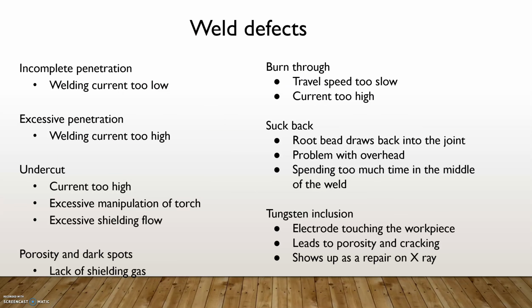Pages 6 and 7 show some weld defects. Incomplete penetration: welding current is too low. Excessive penetration: you have too much current. Undercut can be from current too high, moving your torch around too much, or your shielding gas flow too high. Porosity is from lack of shielding, and if you see any dark spots around a weld, that's also from lack of shielding gas.